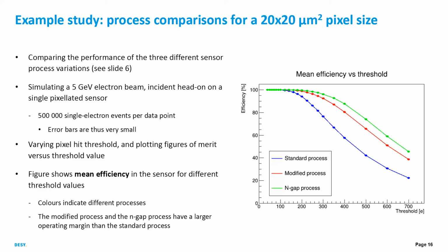And we can compare the performance of them. We simulate here a 5 GeV electron beam incident head-on on a single pixelated sensor, doing 500,000 events per data point. So there are error bars here, but they're very small. And by varying the hit threshold and plotting the figures of merit, we can find graphs like this one. This one shows the mean efficiency on the y-axis and the threshold on the x-axis. What we can see is that as threshold increases, the standard process loses efficiency earlier than the modified and the NGAP processes. So basically, the modified process and the NGAP process have a larger operating margin than the standard process, so we can operate at high efficiency across more thresholds. The NGAP has the best efficiency of all three.